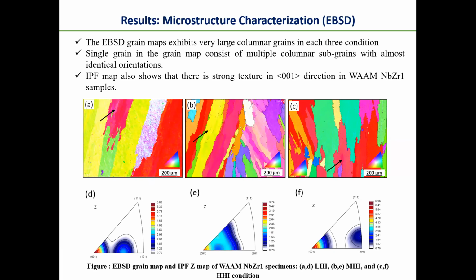Then we did the EBSD analysis to find the grain morphology. This shows that in each condition, the EBSD map shows very large columnar grains in all 3 conditions. Each large columnar single grain consists of multiple columnar subgrains with almost identical orientation. The subgrains could be identified due to the slight mismatch in the color coding, which are shown by the black arrow. The IPF map also shows a strong texture in the 001 direction, which is common in AM components due to the large thermal gradient in the build direction.